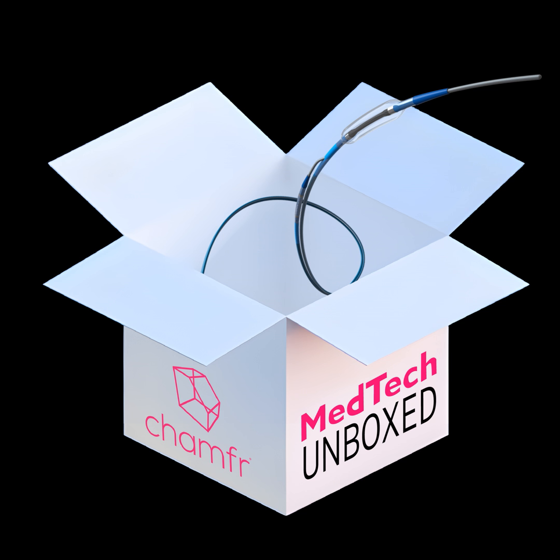With all of that, we also need to be really concerned about how we do venting in the tools from a couple different angles. So one, PEEK is a relatively gassy material. While it's molten and it fills in, it creates a fair amount of off-gassing, and that gas needs to go somewhere. Similar to that, any mold cavity, if you close it up, you have air inside of that cavity. And traditional molds just fill that and have vents in the mold that allow the plastic flow to push the air out through the vents.